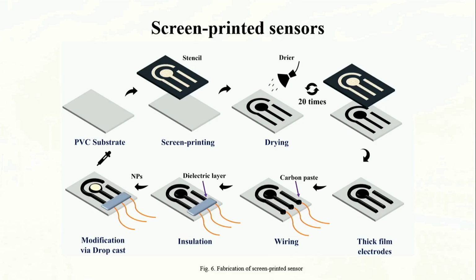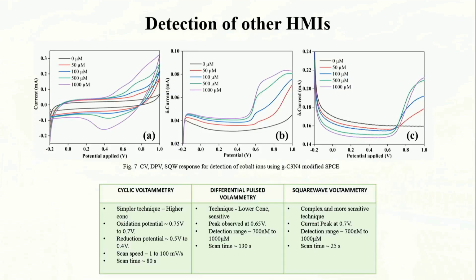Later we wanted to make it into a flexible, easily usable, portable sensor, so we used a screen printed sensor. Here we use screen printing techniques where we coat the carbon layer up to 20 times. At the end, all these electrodes are made of carbon, and the working electrode is modified with graphitic carbon nitride. We ran CV, DPV, and square wave voltammetry techniques for these screen printed sensors.